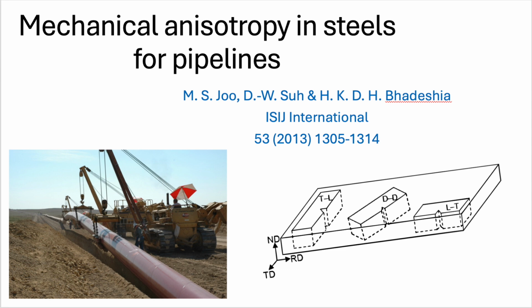But I gather the science isn't totally settled on how much texture matters compared to, say, residual banding. No, there's definitely debate in the literature. Some studies, particularly looking at the brittle transition in X80, find strong links between texture and toughness variation. Others argue that even in clean steels, subtle microstructural variations, like very fine banding, might still be playing a bigger role than texture. So it's complicated, the interaction between all three. It's essentially complex, as one source put it. Inclusions, banding, texture, they're all created or modified by the same rolling process, so they're often linked. Teasing out the exact contribution of each is really challenging.